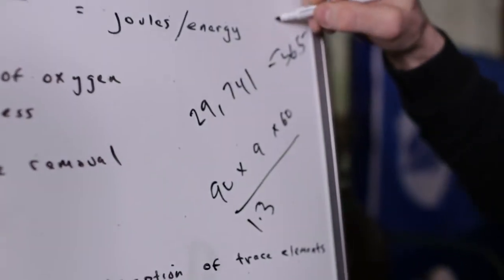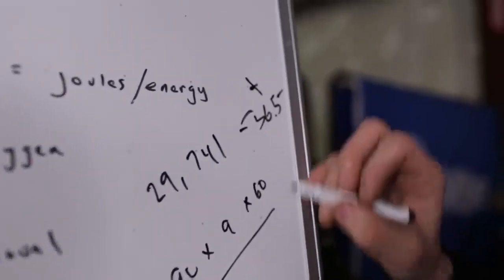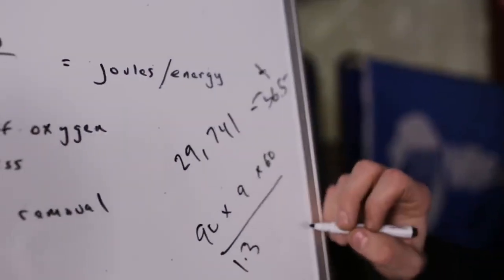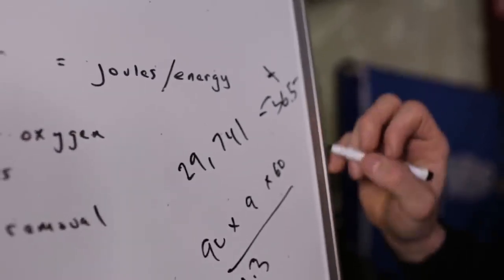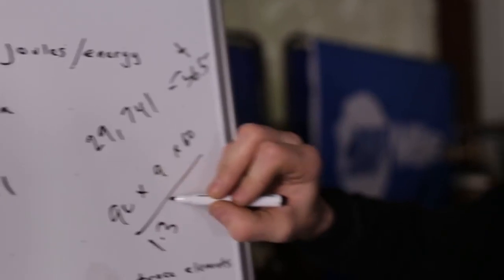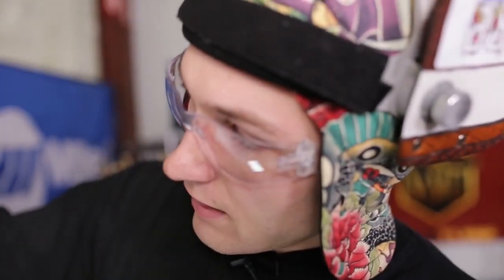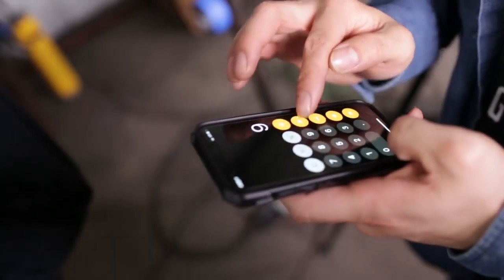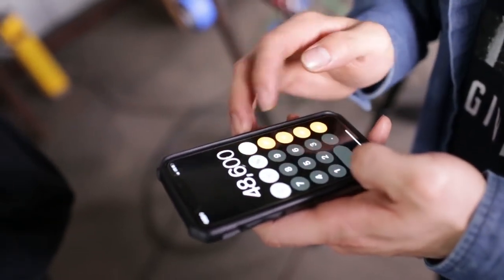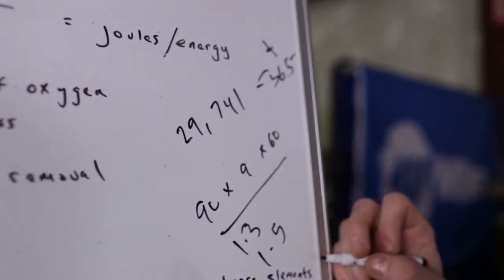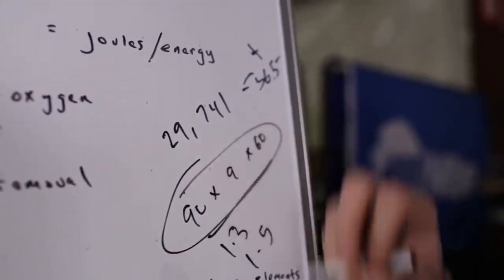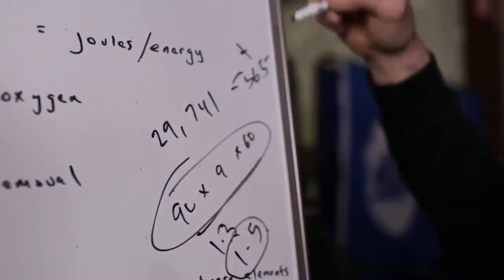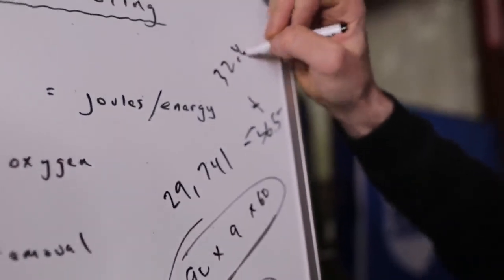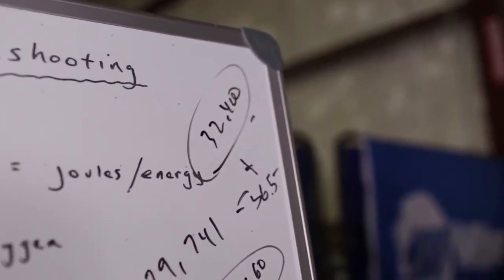So at 37,384 we're a little bit over the maximum. Essentially we have to speed up. An inspector might come and tell you, hey, you're going a little too slow, speed up, get a little more distance. So take 90 times 9 times 60, divided by 1.5. Now that we traveled 1.5 inches instead of 1.3, same everything, we sped up our travel distance and we get 32.4. That's how welding procedures typically work, and that would be allowable.